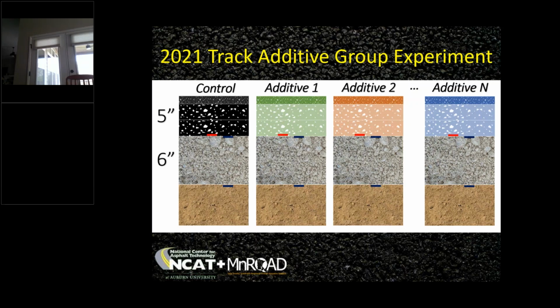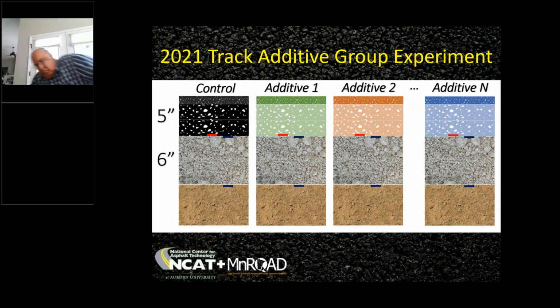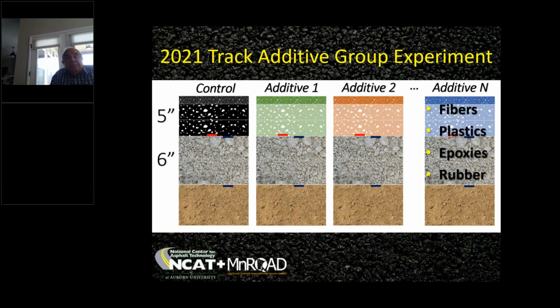So we know from past research that with our base and our subgrade, 5 inches of asphalt fails after just a couple of million ESALs, 20 to 25% of the way through one of our traffic cycles. So this is a very aggressive experiment in order to quantify the structural contribution of these additives, like fibers, plastics, epoxies, rubber, anything else that might come along.